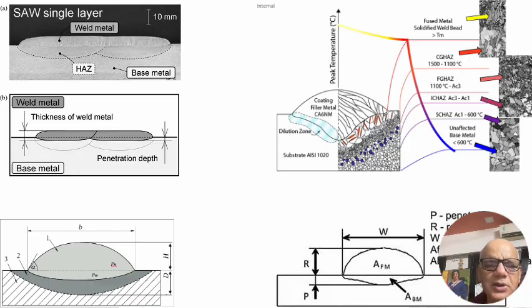So we may use a slightly higher arc length for overlay, which we don't use in our butt joints, because there we are concentrating more on penetration. Here our focus is a very shallow penetration, a wide bead, and a good angle. The angle as shown here should not exceed 60 degrees. Ideally it should be between 45 and 60. It should have a very smooth profile, but if it goes beyond 60, it becomes too sharp for the subsequent run to get properly deposited.